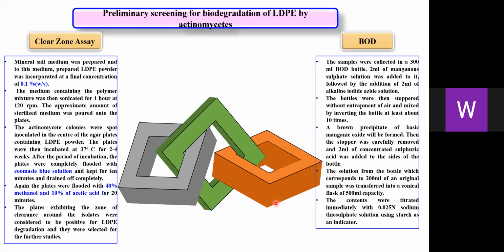Preliminary screening for biodegradation of LDPE by actinomycetes was done by clear zone assay and BOD. Clear zone assay is a tool to assess the degradation of LDPE by secretion of enzymes to depolymerize the polymer and utilize it as a carbon and energy source. As a result, a zone of clearance was developed, which indicates the initiation of biodegradation by standard methods. BOD was done to estimate the utilization of oxygen by the microorganism for degradation by the standard iodometric method.